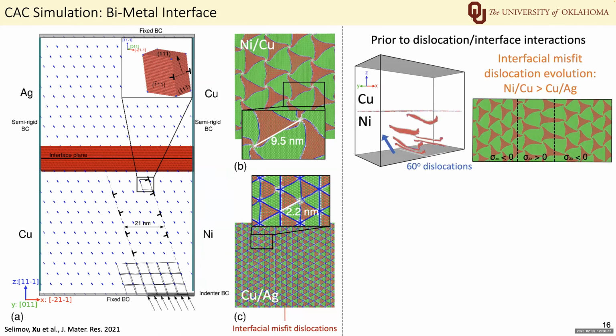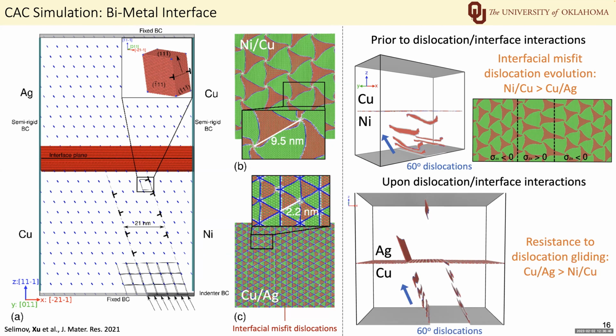interfaces. So we first find that even before the dislocation actually interacts with the interface, the long-range stress field of the dislocation pile-up causes the evolution of interfacial misfit dislocation, and the evolution is more pronounced in the nickel copper interface than in the copper silver interface. Then upon the dislocation interface interaction, we find that the copper silver interface is a stronger barrier to dislocation motion than the nickel copper interface. That is mainly because the copper silver interface has a higher interfacial misfit dislocation density.